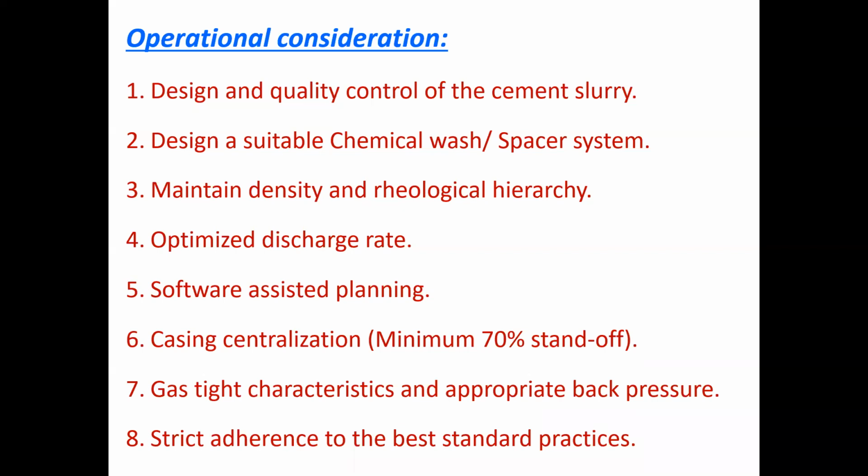For example, if I am using an oil-based mud, a synthetic oil-based mud system, then I need to have something, because that oil is present in the mud. That oil cake has to be removed completely. Otherwise, proper bonding will not be there between the cement and the casing, and the cement and the formation. To remove that, what do we add? We add surfactant into the spacers.